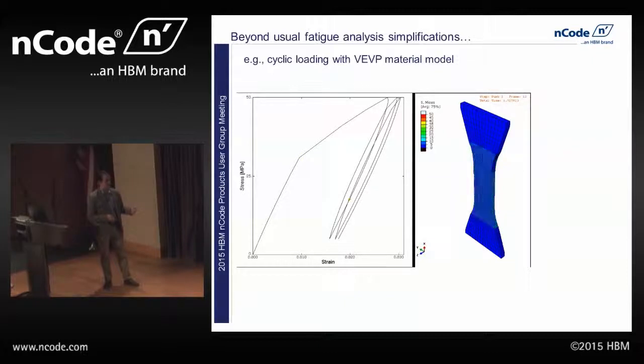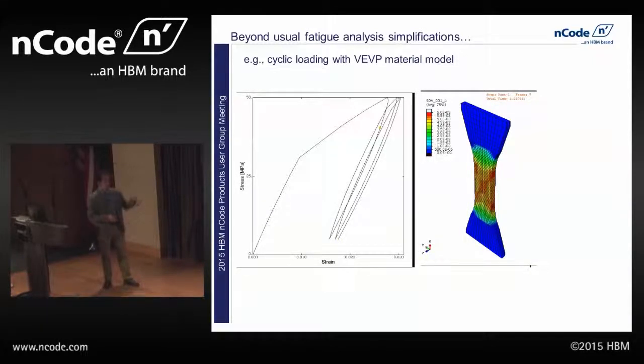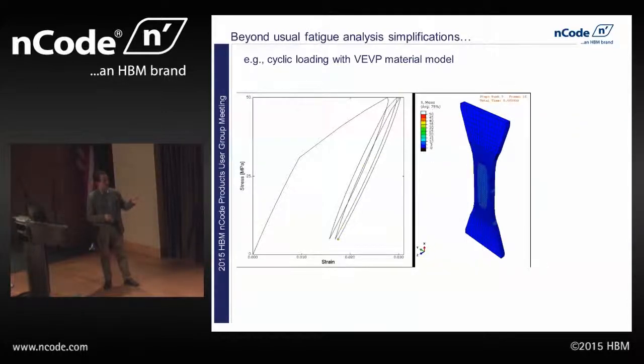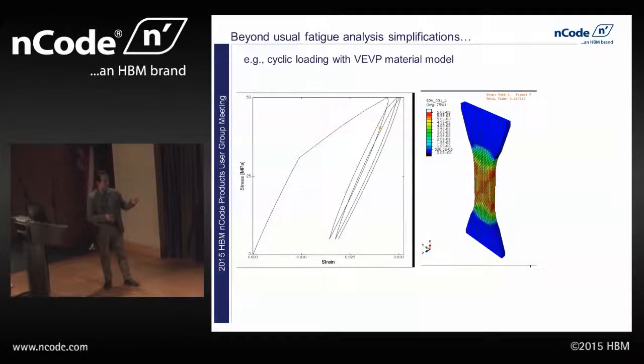And so what you see here is an example of a finite element analysis where we're basically doing some low cycle fatigue loading. So if I go back there, you can see the load kind of gets applied and then taken away and applied and taken away. And what we want to know is, can we predict the damage happening in this cycle fatigue? And so what you see here is the plastic strain in the composite material happening. And indeed, when we apply this viscous model, you're able to see that damage in the composite build nicely. So a little bit off topic, but just something interesting to share and to keep in your mind as you're dealing with these materials.